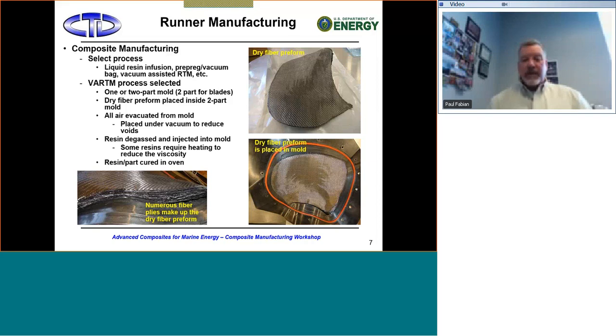But in this process, you have a dry fiber preform that you place inside the mold. You degas or evacuate all the air from that dry preform. And when I say dry preform, I'm talking about lots of layers stacked up on top of each other. And so you can see down in the lower left, in some cases, we had over 100 plies of fiber stacked up to get the proper thickness and get the properties where we wanted it. But once you degas that and get all the air out, then you inject resin in there. The resin is degassed to make sure you don't have entrained air in the resin, and then that's injected into the mold and the resin impregnates and wets the fiber. Once it's fully wetted, then you cure the part.